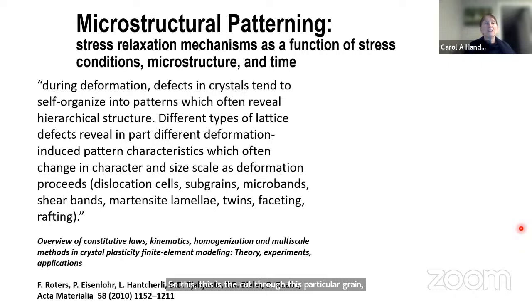So one of the things that I really was taken by in this paper, it was a review paper, was the idea that there's certain pattern formation for stress relaxation in polycrystalline films. That during deformation, defects in crystals tend to self-organize into patterns, which often reveal hierarchical structure. In our case of tin whiskers and some other stress relaxation, they actually have signatures that can be used to identify them. So there are different types of lattice defects that reveal in part different deformation-induced pattern characteristics, which often change in character and size scale as deformation proceeds. So there are many different things that happen, and they happen over time.